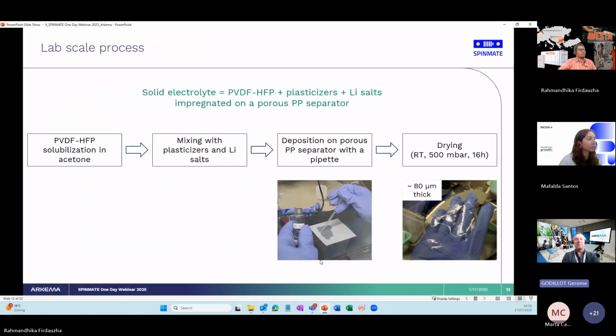So now we move to the second part, which is manufacturing at lab scale. This process was mainly developed by CIC energiGUNE, our partner in SPINMATE, and it ended up with solid electrolytes composed of PVDF, HFP, some plasticizer, some Li salt, and all this composition was impregnated on a porous polypropylene separator. The process they use at lab scale is done in the glove box. First, it's the PVDF HFP solubilization in acetone. Then it is mixed with the plasticizer and lithium salt. And then it is deposited manually as a solution.